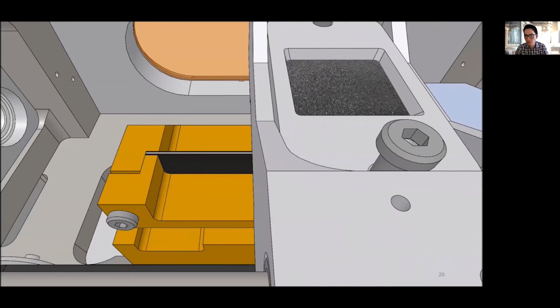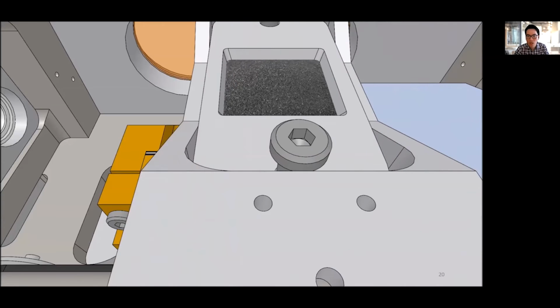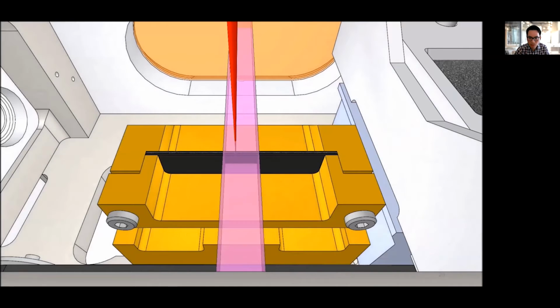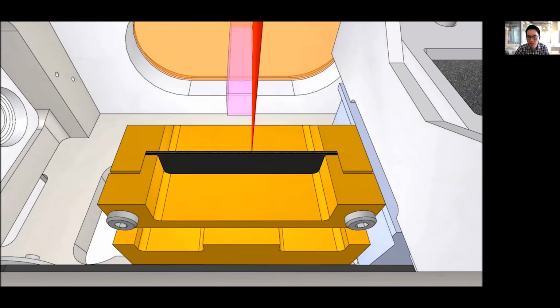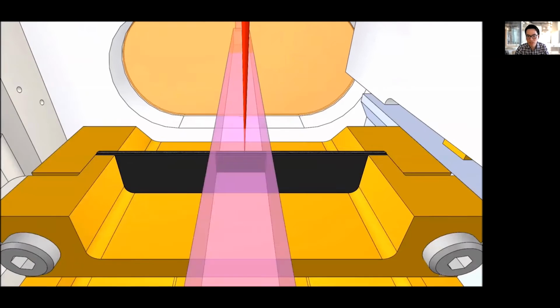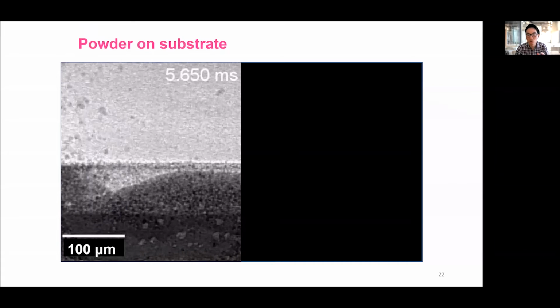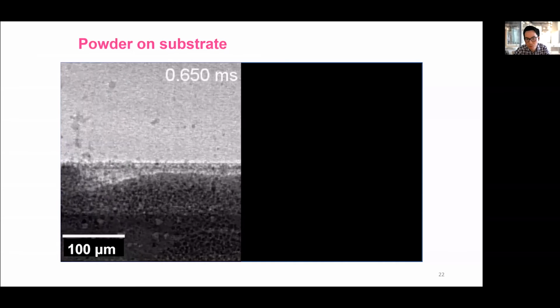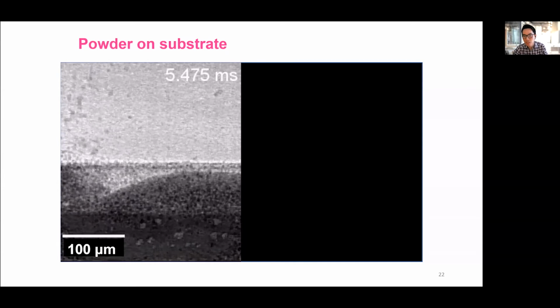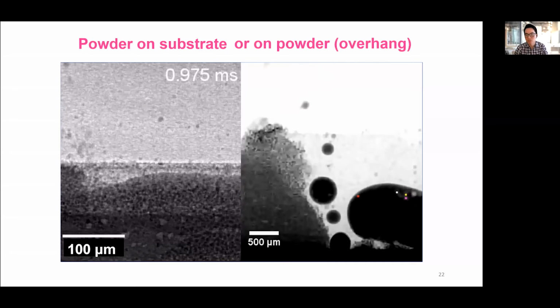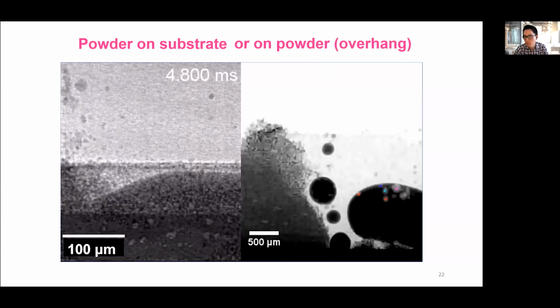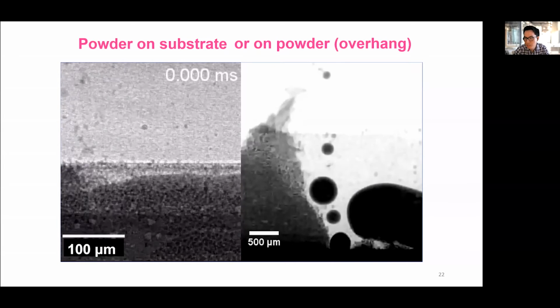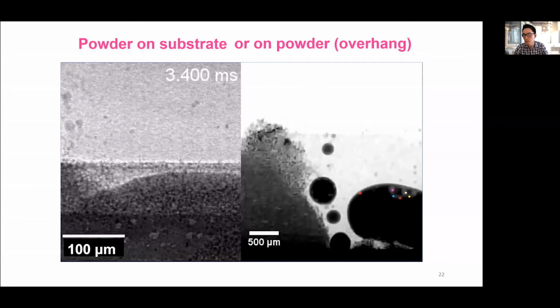So how does it work? You begin with powder spreading. We have a light, laser rastering, and we have X-ray going through, as you can see. These are the images of a laser generated melt pool of titanium, and you can see the melt ejection really happening. The melt pool is forming. On the right hand side, you can see actually there is fluid motion.